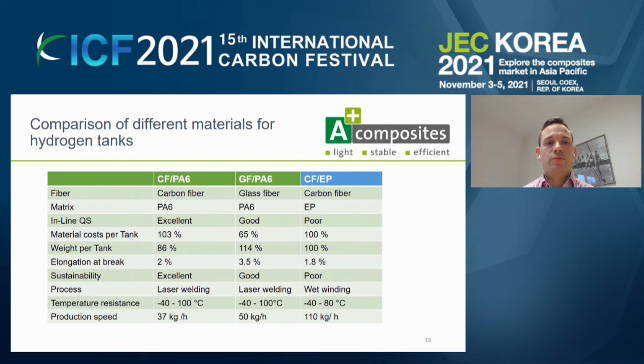And in comparison to thermoset materials, it is nearly impossible to monitor the width and the thickness and the distribution on the vessel, for example, and to find out where really which material is. If you compare now the material cost of the final vessel, it is very surprising at first that the material cost for the carbon fiber tape variant in comparison to the wet winding variant is nearly the same level. This is due to the better use of tensile strength, or the better use of the fiber, than with the wet winding process. And therefore you have to apply more material to the vessel, and this leads to a higher vessel weight in comparison to a thermoplastic solution.